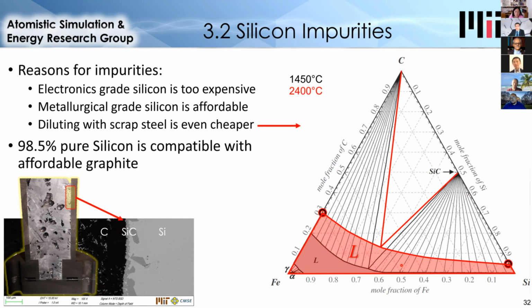Now this red curve is an estimation based on the 2 points shown, since a ternary phase diagram was not available at these temperatures. But what this shows is that definitely as you add iron, the solubility of the solid carbon in the iron silicon mixture will increase. And so if it's not protected by the silicon carbide layer, adding iron will only exacerbate the dissolution issue.